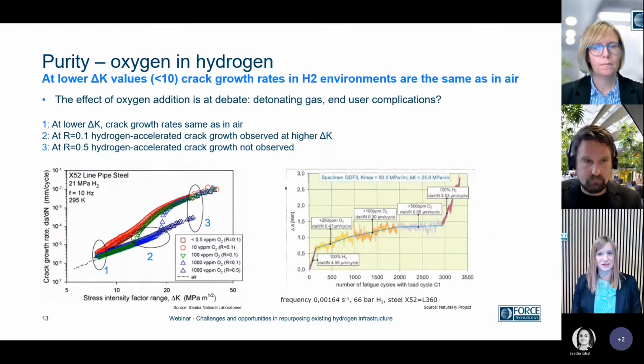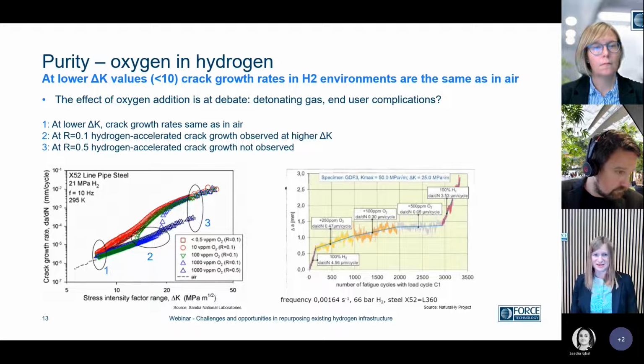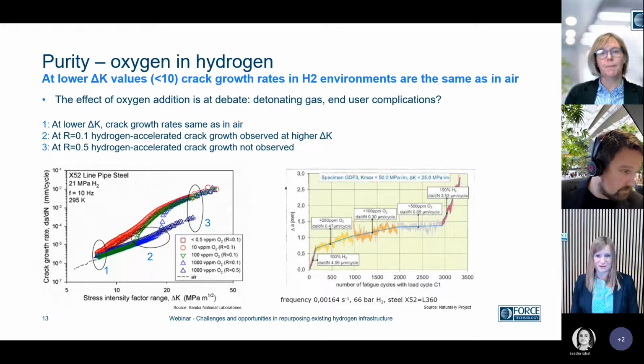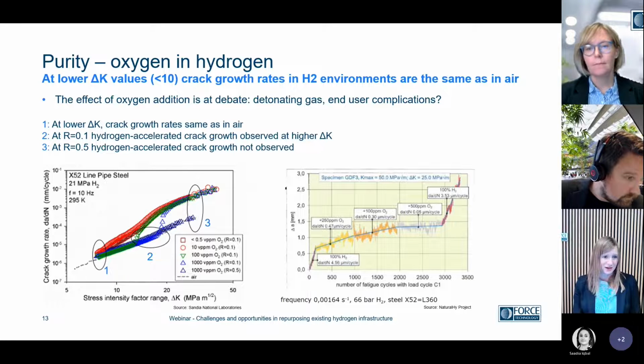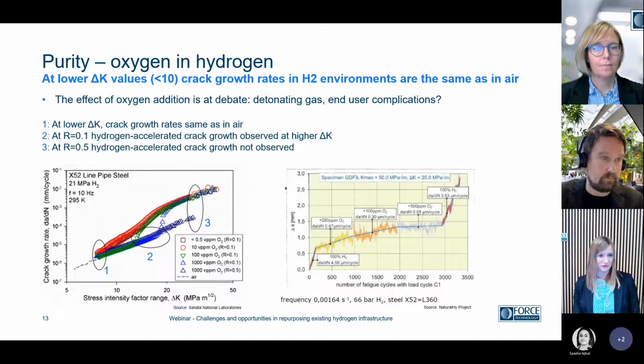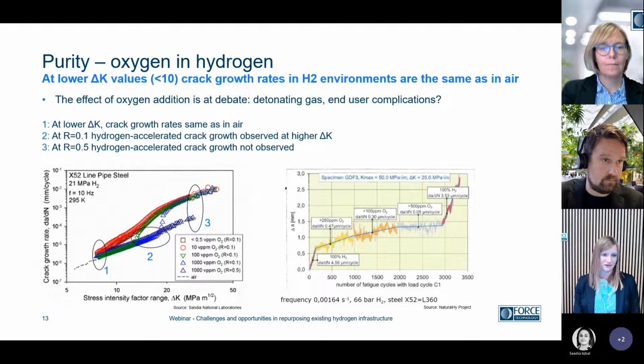And that's been discussed mainly, I guess, on a European level. And it's still a debate, because would it be possible to add a bit of oxygen to the hydrogen infrastructure to inhibit the hydrogen embrittlement of steels? Well, I guess the risk of a detonating gas and end user complications are burying that at present, but studies on the effect have been carried out. As we see on the plot from the right, we don't have an effect of hydrogen nor the oxygen at very low delta K levels, but the oxygen has an inhibiting effect, especially at intermediate delta K levels.